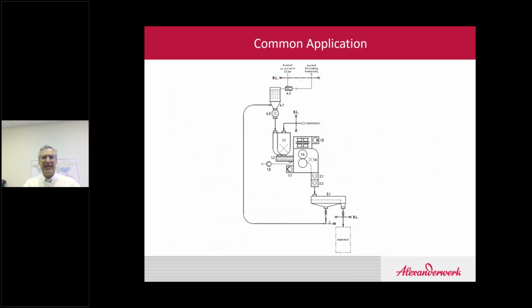Here will be a typical setup of a roller compaction system. You can see you have a feed system introducing material into the feed hopper. The feed hopper transports the material to the counter-rotating rolls. The material is size reduced by the RFGs. And then sometimes there's a screening deck also, which screens out any of the fines if that's necessary for part of your process. Those fines can be recirculated and put back up into the feed hopper so we can produce those granules between a certain particle size distribution that you're looking for.